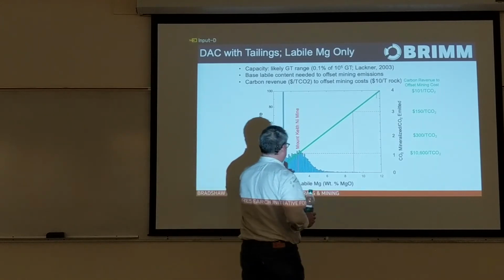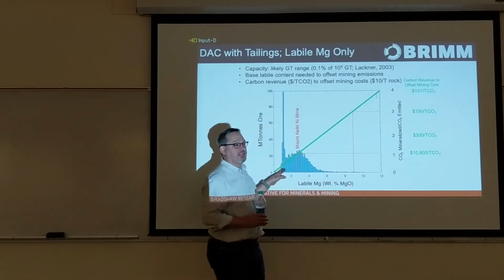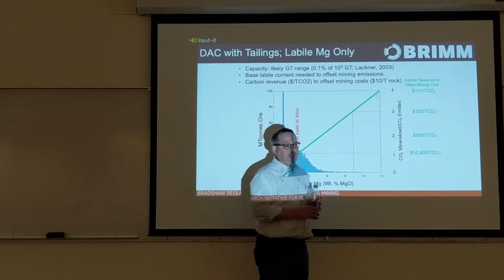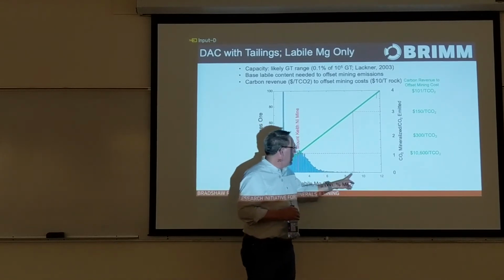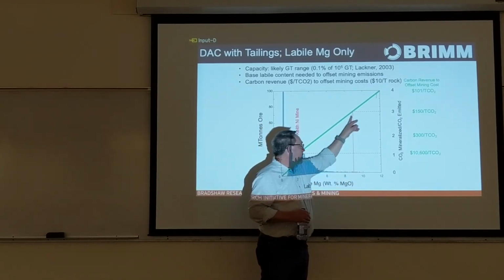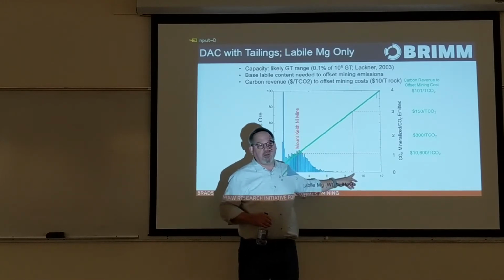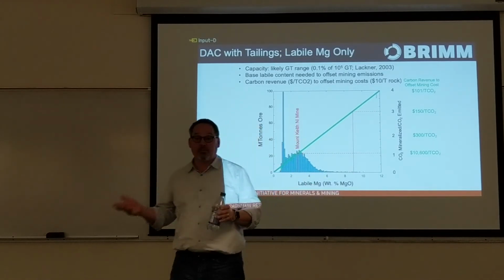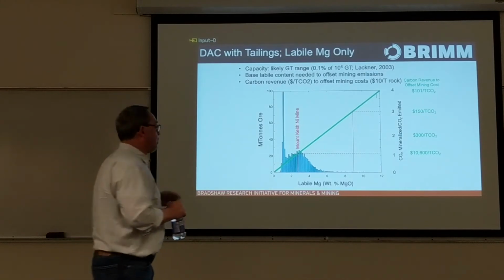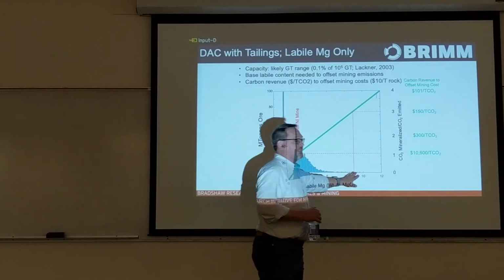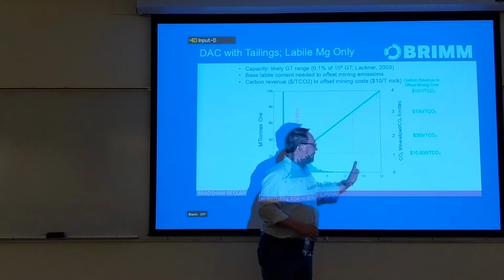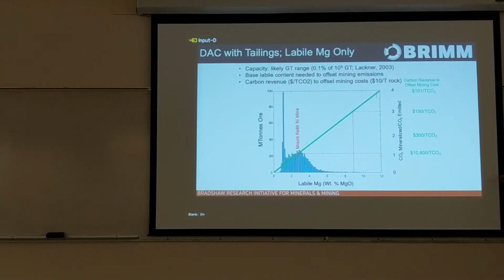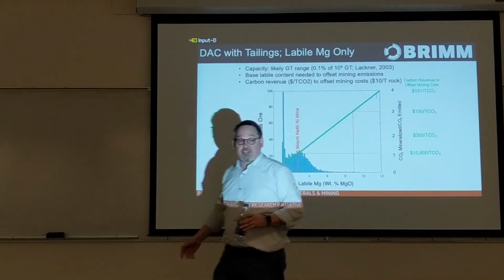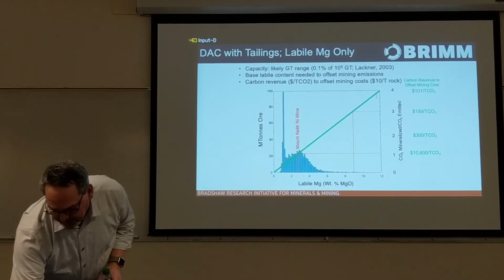And it seems ridiculous to potentially apply this to the crust. We haven't currently mapped the crust for labile magnesium, but the Dumont nickel mine in Quebec has a reported average labile magnesium content that lies in here somewhere, and that's about a 1 billion ton deposit. So there are reports at least of large scale deposits that have bulk average labile magnesium contents that correspond to this amount. So it's maybe not too crazy to think that these things might actually be usable for this purpose.